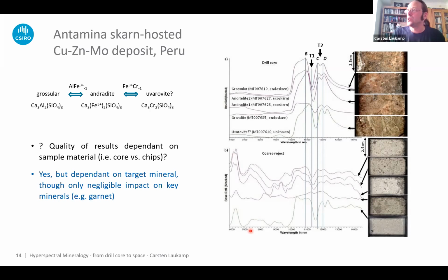And that's what we can do here, no matter if we look at drill core reflectance spectra, like shown here on top, or reflectance spectra from coarse reject. So you see those squiggly lines from these different sample materials. They look quite a little bit different. And especially with the fine-grained material, we're introducing this volume scattering here, around 7,000 to 8,000 nanometers. And that all distracts us from extracting the right minerals.